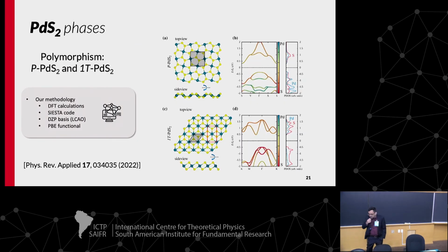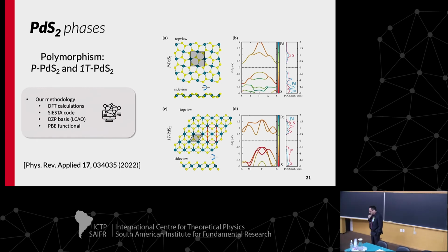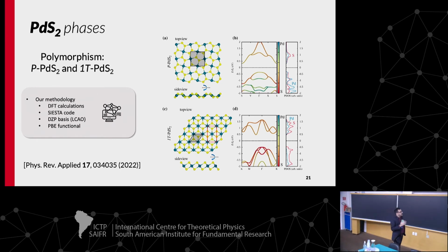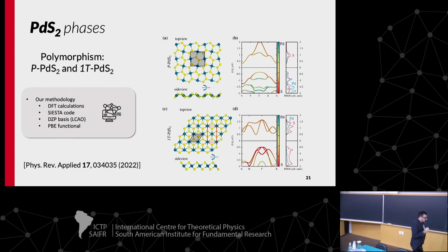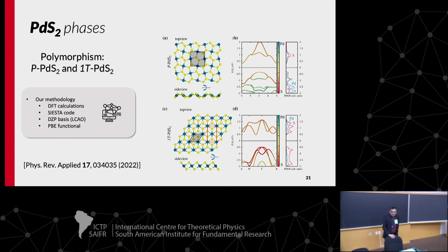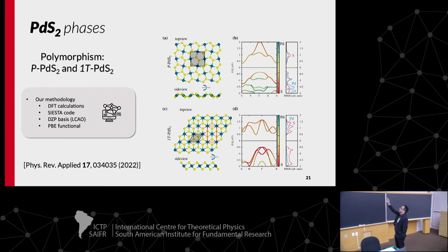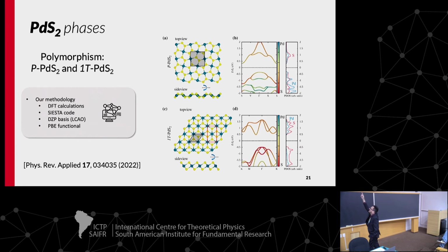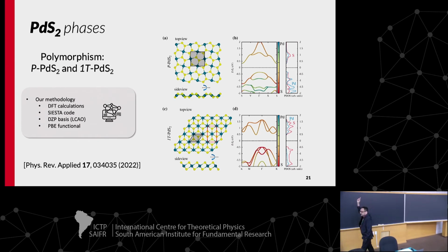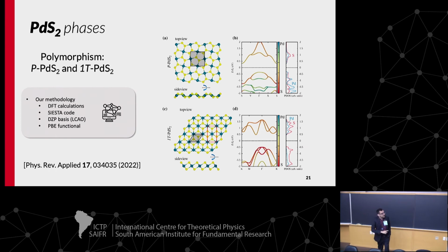So one of my PhD students did some calculations with a similar material, not MoS2, but we proposed to study another disulfide, like palladium disulfide, because we also have two different phases. In this case, the pentagonal phase and the 1T phase. Both phases are semiconductors, different from MoS2. MoS2 has a semiconductor phase and a metal phase.